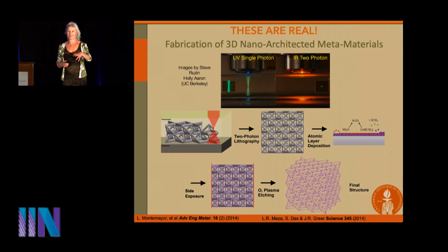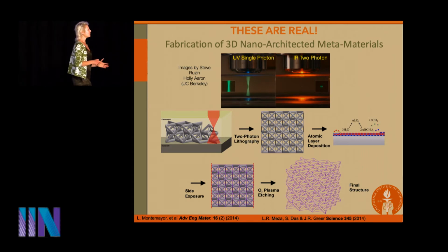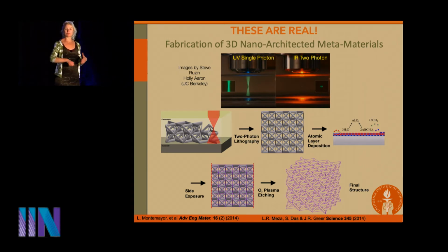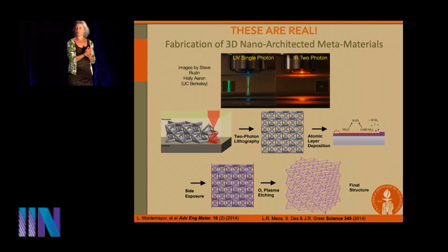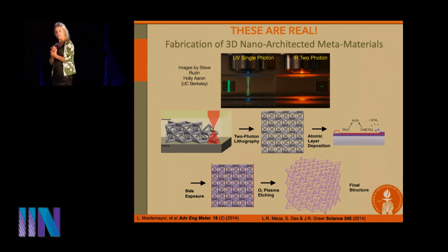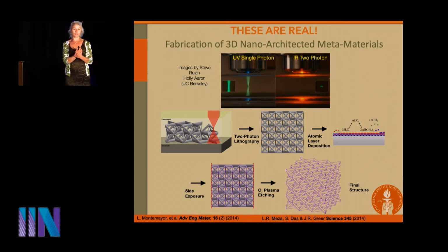By the end of this talk, you'll see that that's not the case, but that's what most people do that use this technique. Now, we're not going to go build airplanes or anything useful out of these. So what we do after that is we often coat these scaffolds with the material we actually are interested in. Now, how many of you are familiar with ALD, atomic layer deposition? Quite a few. So in the ALD community, they say, we can deposit anything you want for you as long as it's alumina. So here's some alumina.